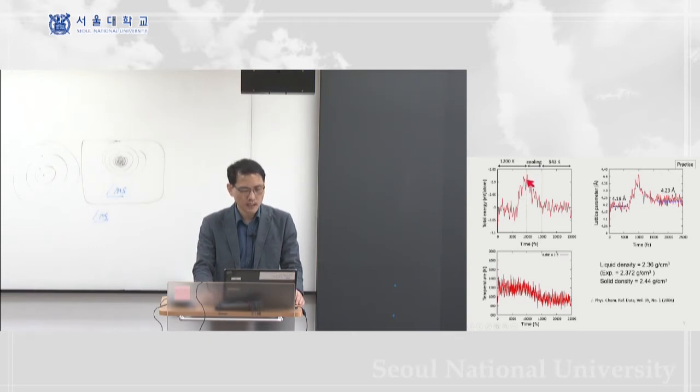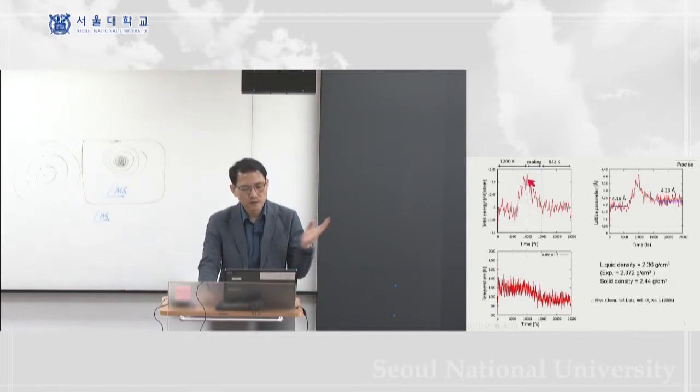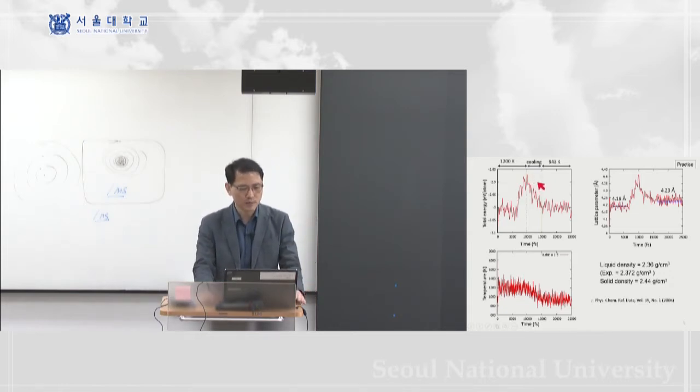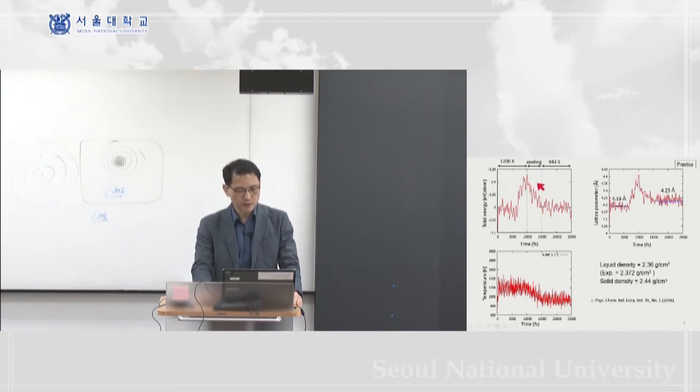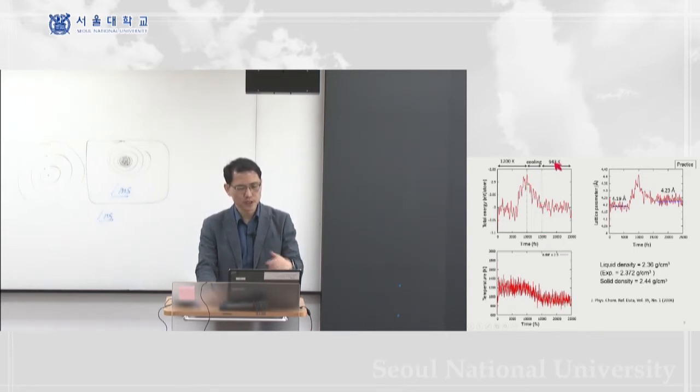All right, and I think that you actually have to increase the simulation time a little bit longer. I'm not sure why we have stopped here, but I think at least you need to go at least 10 picosecond more to fully equilibrate at 1200 Kelvin. All right, then am I right? Okay, and then you gradually cool down over 5 picosecond to your target temperature.